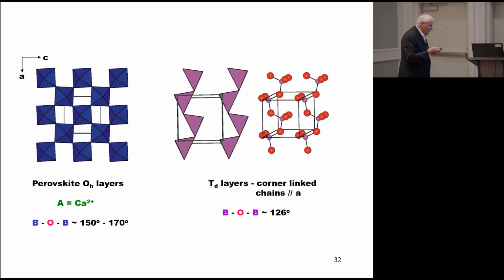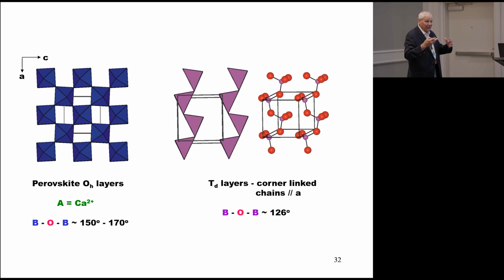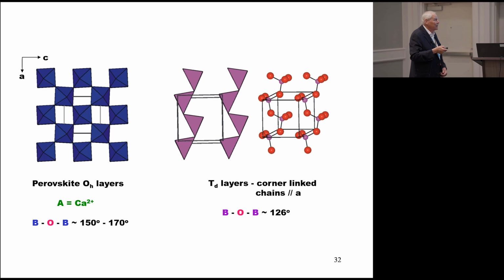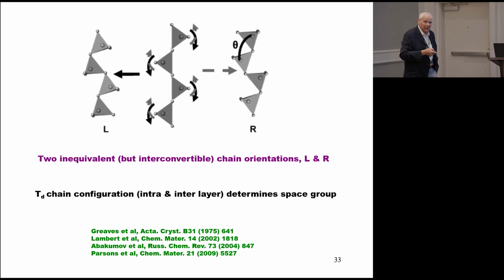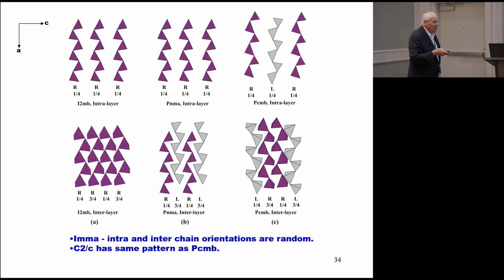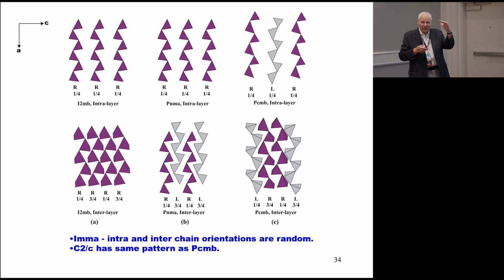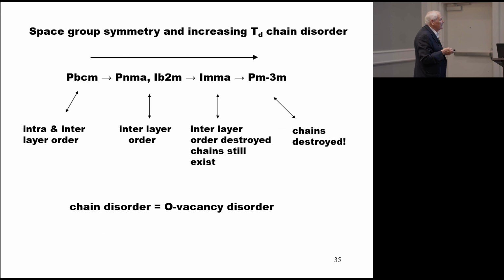Okay. The perovskite layers, the octahedral layers, are just like perovskite, they're corner-shared octahedra. The tetrahedral layers are also corner-shared, but of course, they're sharing only one corner. And it's the tetrahedral layers that define the overall symmetry for Brown-Millerites. I'm not going to go into too much detail, but as it turns out, you can have both right-handed and left-handed chains. The orientation of the chains, both within the layers themselves and between the layers, determines the symmetry. And you get a whole range of mainly orthorhombic space groups, depending on the relationship between the intralayer correlations between the chains and the interlayer correlations.